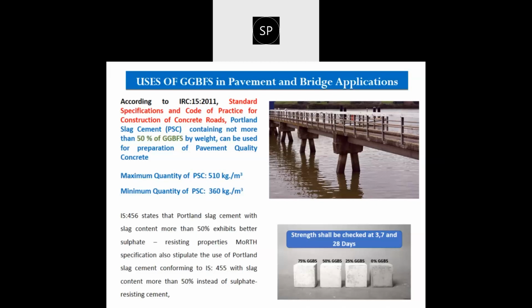JSW Cement and Tata Steel are producing this Portland slag cement, and recently Ultratech has also started manufacturing it. So particularly in the eastern part as well as in Maharashtra and Karnataka, the availability of Portland slag cement is very good, and it can be utilized as a substitute for OPC and PPC for pavement quality concrete work. The maximum quantity of PSC is once again limited to 500 kg per cubic meter, while the minimum quantity is prescribed as 360 kg per cubic meter for the preparation of pavement quality concrete.